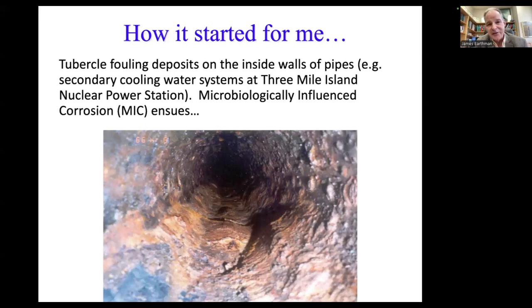I'm going to be trying to talk to them about what we're doing in the not too distant future, but they had this problem with their secondary cooling water system. That system basically took in river water. 3 Mile Island is actually on a river, and they bring in water from the river and they use it in their secondary cooling water system, which cools the primary system, which has pristine treated water, very clean water that goes into the nuclear part of the plant. But that system has to be cooled by the secondary system, and it just has coarse filtered river water.